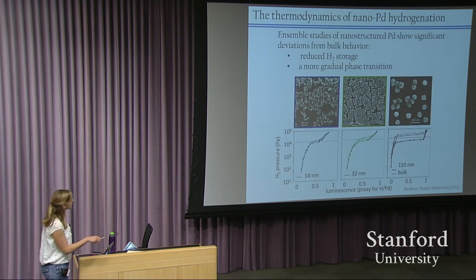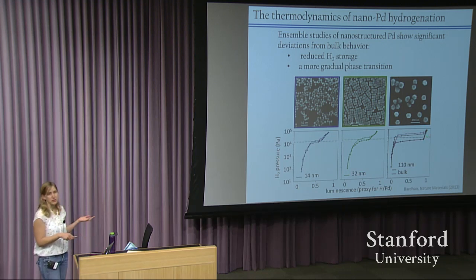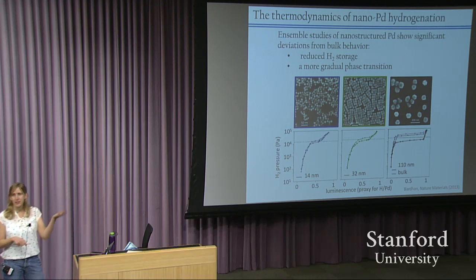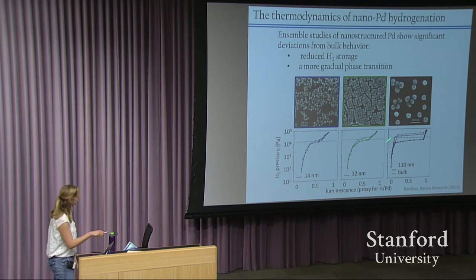So just working through each of these electron micrographs and the associated isotherms, they're basically fixing the temperature and mapping out the phase as a function of hydrogen pressure. Here are larger nanoparticles that are 110 nanometers across, and they're overlaid on an isotherm for the bulk material, and you'll notice they look quite similar. One of these graphs corresponds to loading, so they're increasing the hydrogen pressure, and then they decrease the hydrogen pressure, and this system shows hysteresis. So these particles tend to unload hydrogen at a lower hydrogen pressure than they would absorb hydrogen. So this looks a lot like bulk.